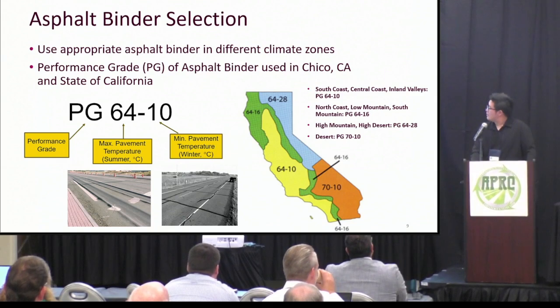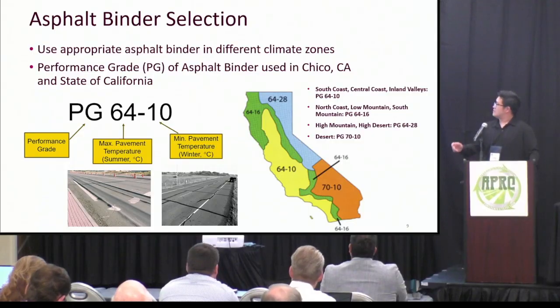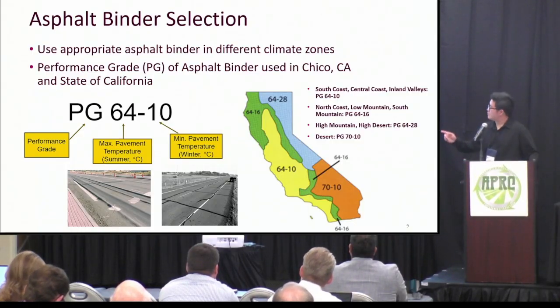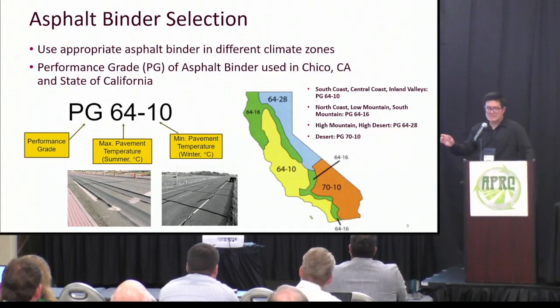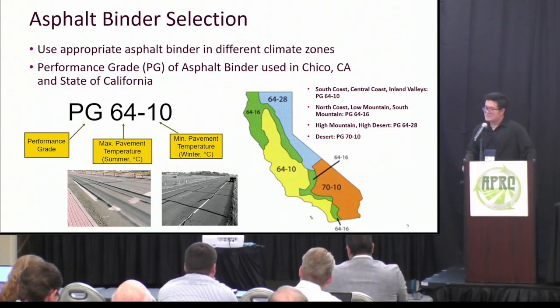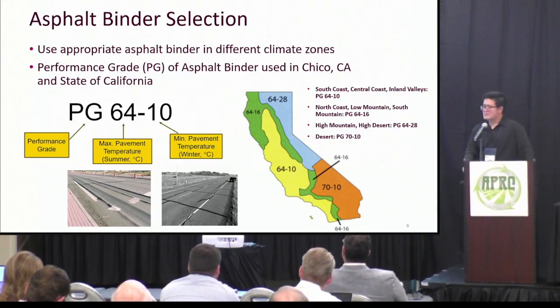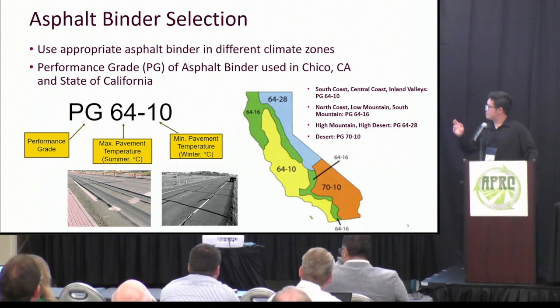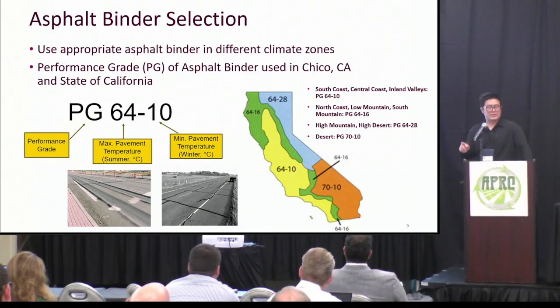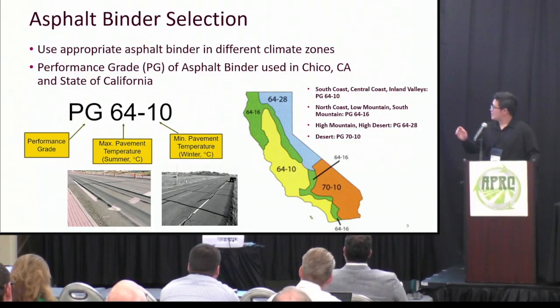And right now, we select the binder, or select the asphalt, based on the performance grade, or it's called PG. So PG 64-10 is the binder used in Chico, where my workplace is. The PG stands for performance grade, and the 64 means this binder can perform well up to a maximum pavement temperature of 64 degrees Celsius. And minus 10 means this binder can perform well at a minimum pavement temperature of minus 10.